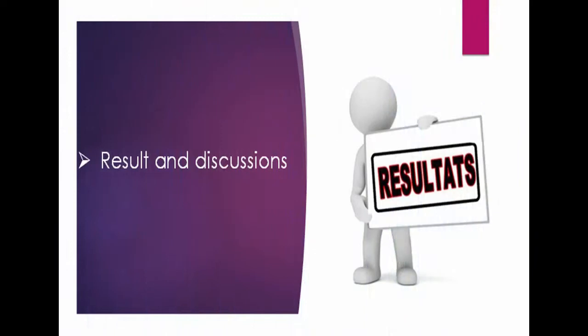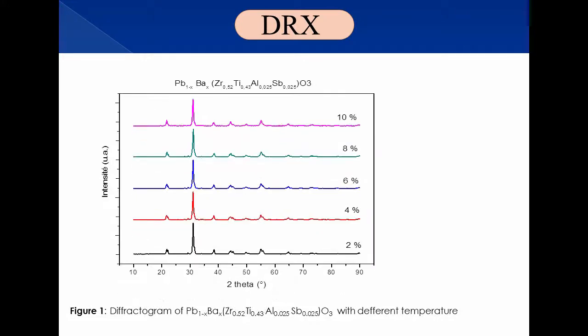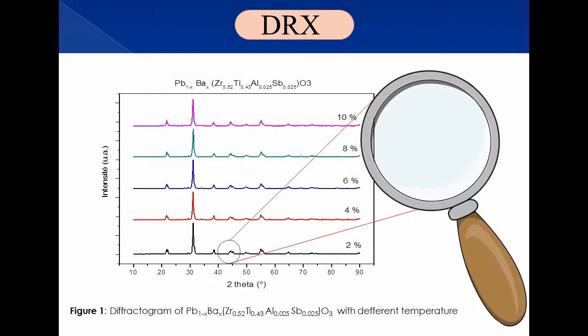Finally, we have seen that all the analyses we have done within the University of Biskra give us almost acceptable results. We were able to conclude the importance of having a composition of biphasic structures, T plus R. The diffractogram shows that all the samples we analyzed are clearly pure, and we got nothing like a secondary phase. And the most important finding in our diffractogram is that we are at the morphotropic phase boundary. To be more precise, we can notice that there are peaks focused in 2 theta between 43 and 46.